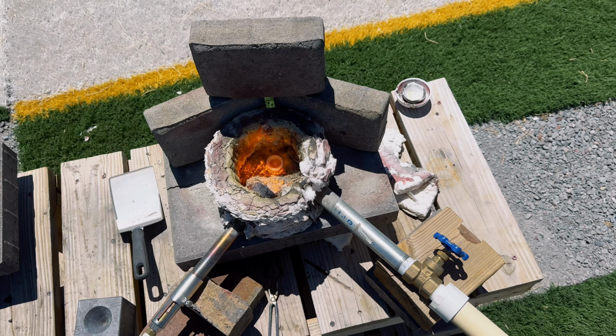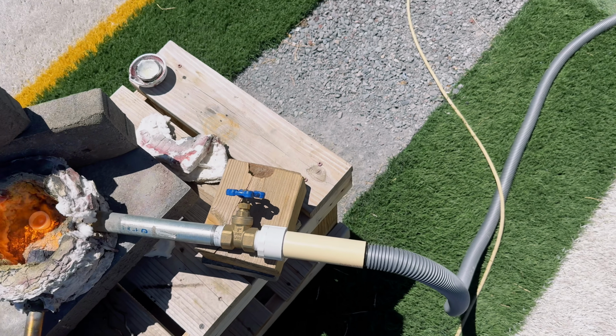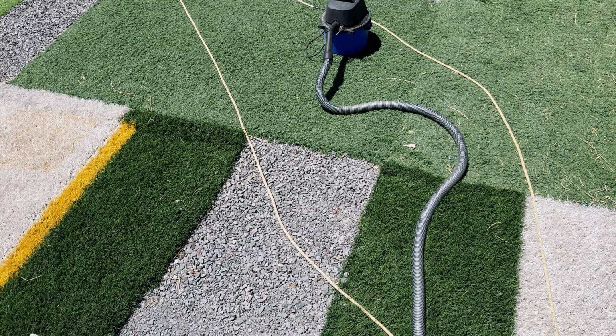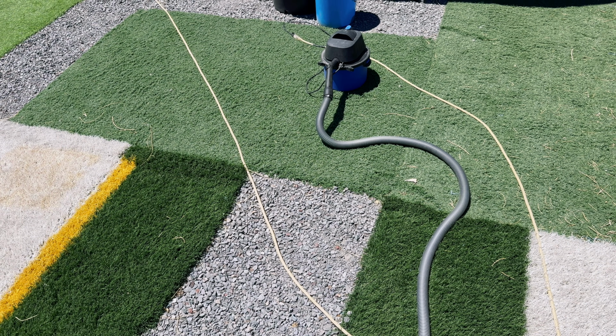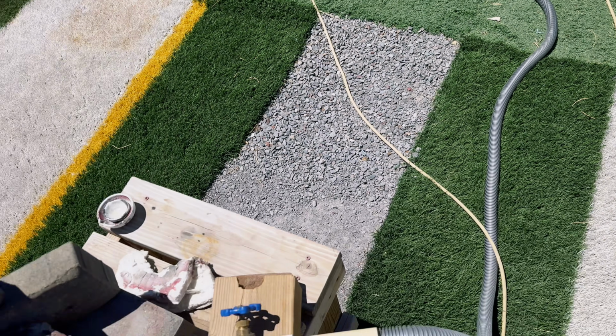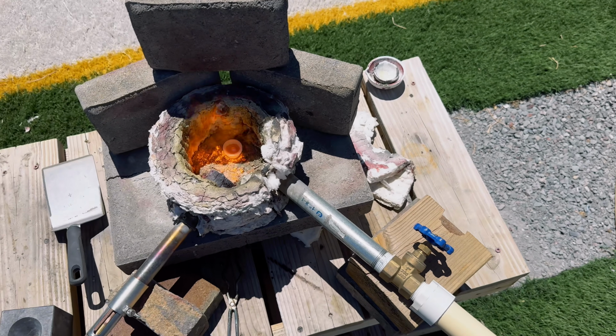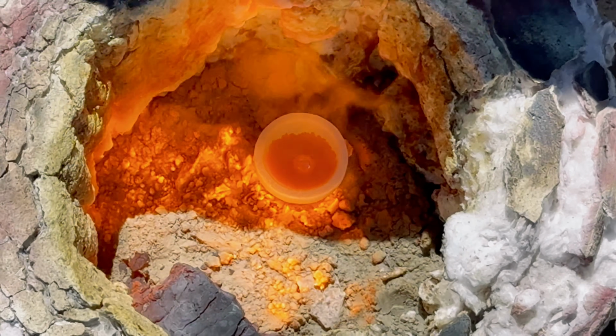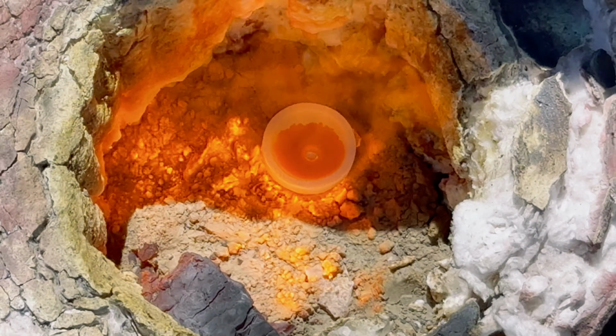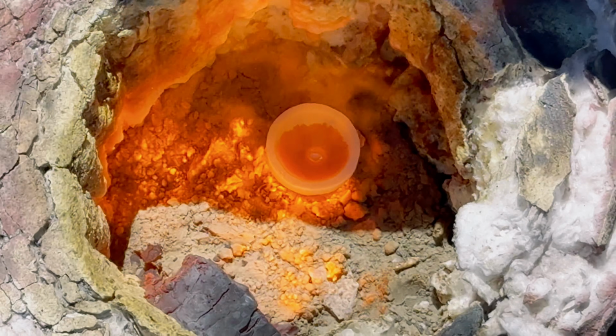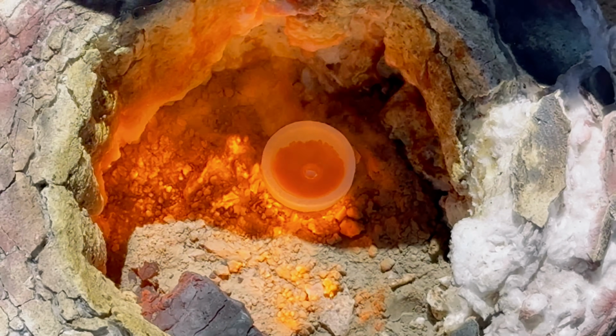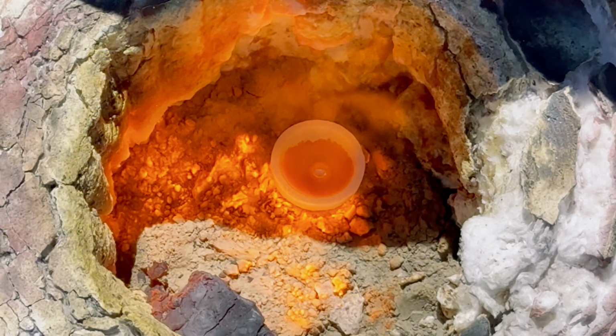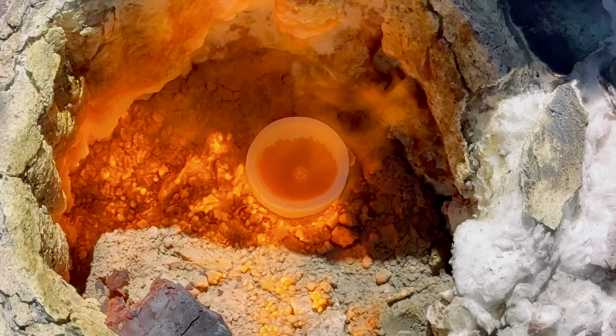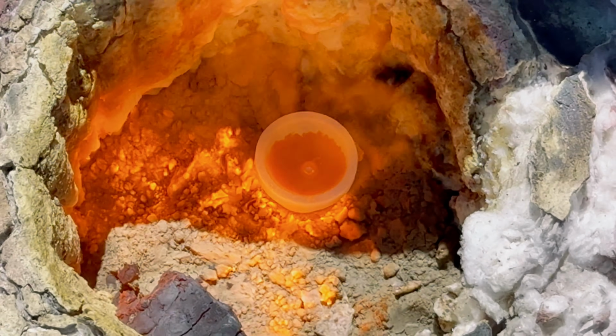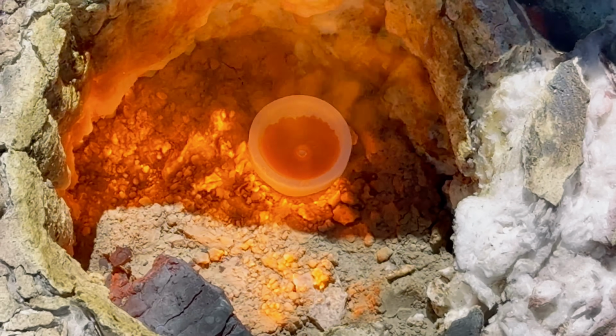Here is my wet-dry vacuum apparatus to blow more air and oxygen into the fire assay. The more oxygen we get into the fire assay, the faster the lead prill oxidizes. When the lead prill oxidizes, the cupel absorbs the oxidation from the lead prill. The oxidation is the oily black film that you see on top of the lead prill, and you can see the black that's in the cupel, and that's the oxidation that the cupel has absorbed.